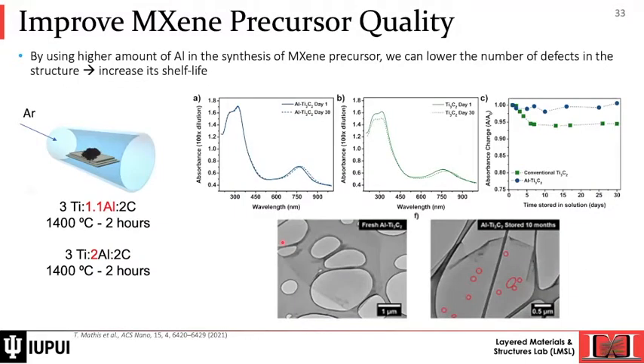The other method that came out from Drexel, from Professor Yury Gogotsi's group, showed that if we modify the MXene precursor synthesis route, we can significantly, up to 10 months, improve the stability of MXene Ti3C2. The way they modified it is very clever and simple. If you change the stoichiometric ratio of the titanium 3, aluminum 1, carbon 2, and add twice moles as for aluminum as needed,